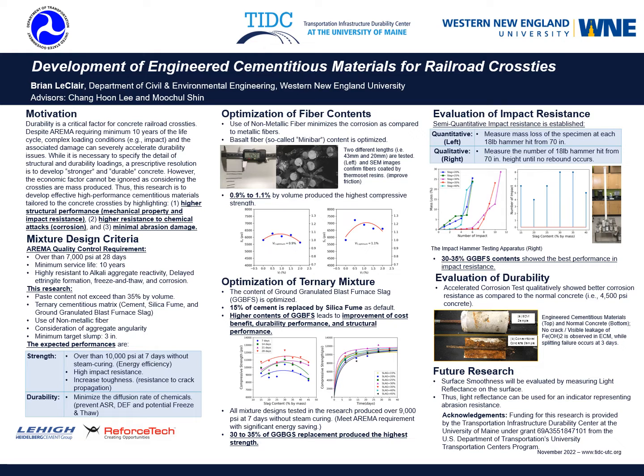On the second graph, we have what we called hits until no rebound. We found that when dropping the hammer onto the samples, after a certain point, the hammer stops rebounding back. For the first drops, before this point, the hammer hits the concrete sample and then bounces off noticeably, usually a few inches off of the sample. However, there's a point in every sample where instead of bouncing off, the hammer hits the sample and sticks into it. This is also usually accompanied by a large chunk flying off of the concrete. This hit where the hammer sticks into the concrete is what we call a no rebound hit. So the second graph shows how many hits each sample took before the first no rebound hit, because after the first one, every hit after that until 20% mass loss is a no rebound hit. As you can see, both 30 and 35% slag mixes performed well in this testing as well.